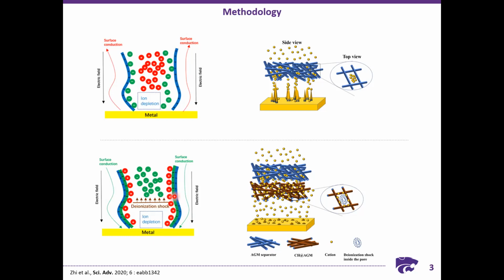What happens is, as the lithium gets plated, there will be a formation of concentration gradient because of the consumption of lithium ions or the zinc ions. As they get consumed, there will be an ion depletion close to the metal surface. In order to have electroneutrality, the counter ions will get expelled out of this region. This will result in a decrease in the salt concentration close to the metal surface. Because of this decrease in salt concentration, the bulk electroconductivity will be low there. However, because of these negatively charged ions in the diffusion layer, there will be a phenomenon called surface conduction.